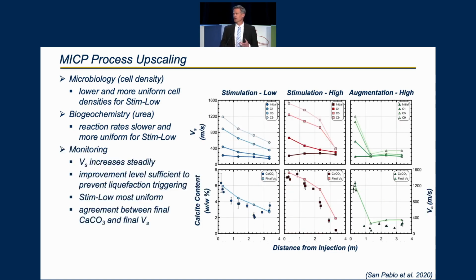We've talked about the strong coupling between shear wave velocity and calcite content. The top set of figures shows, from dark to light, improvement in cementation as reflected by shear wave velocity. The left set of figures is most uniform in terms of the shear wave velocity increasing throughout the treatment course, whereas in the far right set of figures, you can see that cementation was primarily localized near the injection ports.